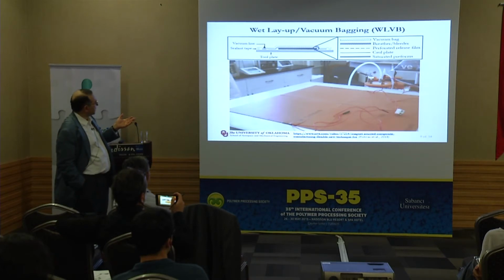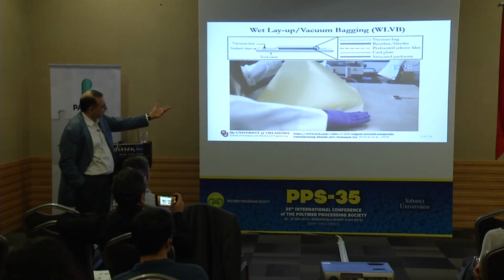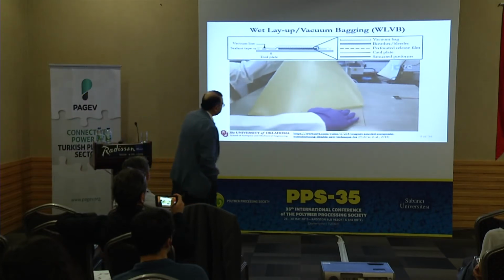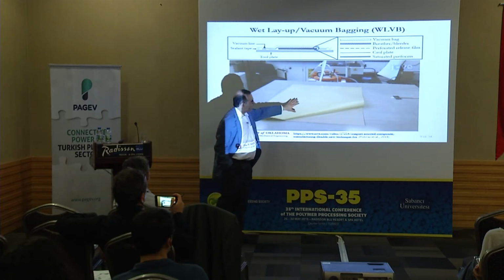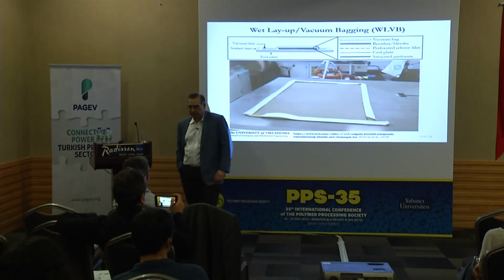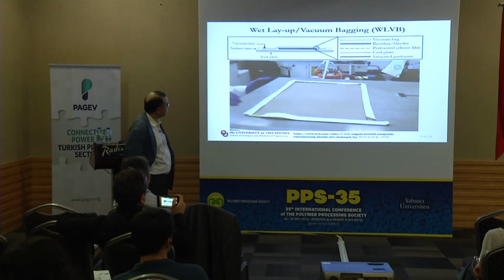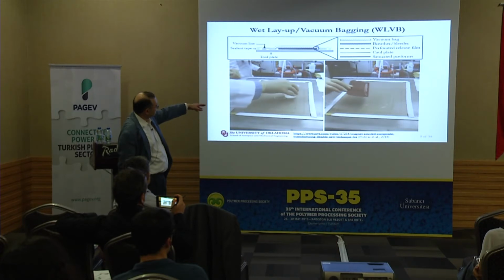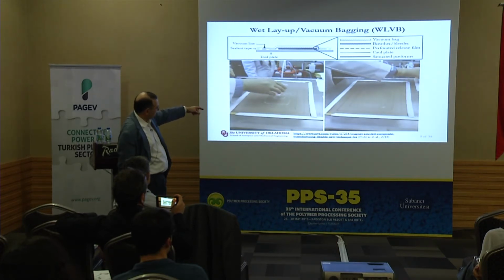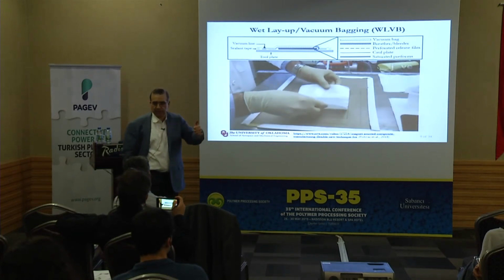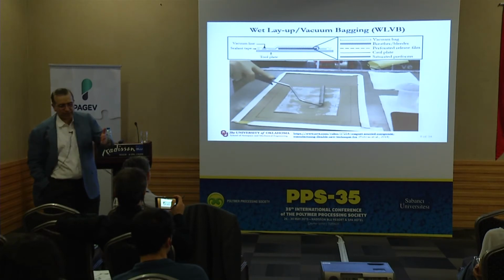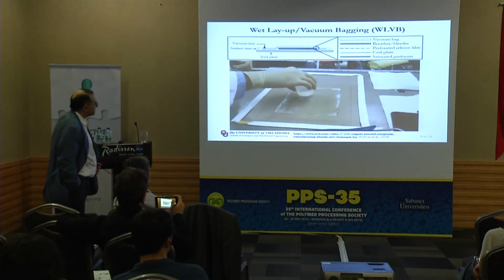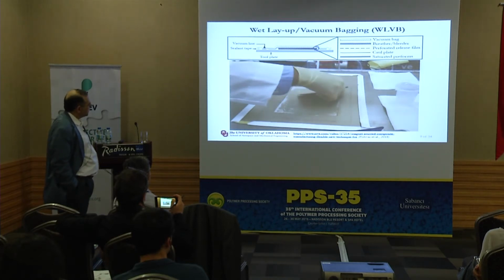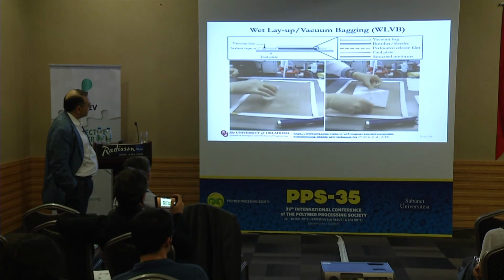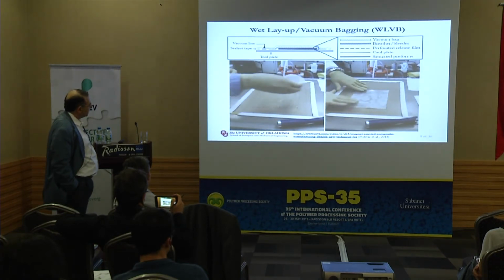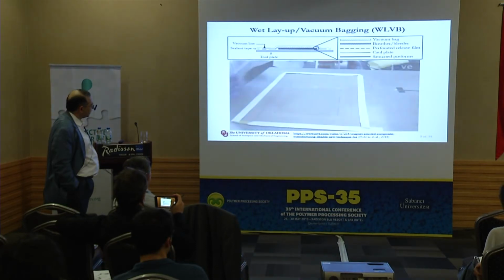We were doing heated wet layup, so these are the heating elements at the bottom of the tool plate. This is a Teflon sheet so that we can easily remove the cured part from the tool plate, so that it doesn't stick to the metal. The vacuum port is there. Wet layup, a little bit of resin. Of course, this is mixed with the cure agent now. Once you mix with cure agent, the time starts ticking. You have a gel time of 1 hour, so you have to finish the process. These are my students doing the illustration.